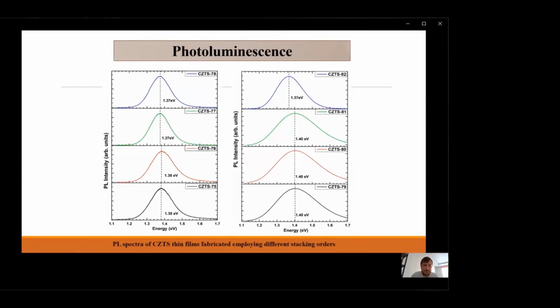This is the photoluminescence spectra of the samples. It's well known that the CZTS samples have a band gap between 1.4 and 1.5. So here you can see this peak is slightly different from 1.4. It's attributed in the literature not to a band-to-band transition, but to a conduction band to acceptor level transition, due to some defect or impurities in the band structure.